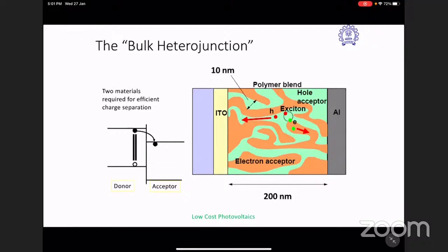Yes, that is very, very relevant, and that is the heart of this whole OPV research, and all the efforts are basically being put in to optimize this nanomorphology to get everything optimal in terms of charge generation, first light absorption, then exciton dissociation, and then charge transport. So how do we look at these interfaces? How about the phase purity of these domains? And you don't want purely phase pure, then you don't have the charge generation. You need phase impure domains as well as phase pure domains for better charge transport.